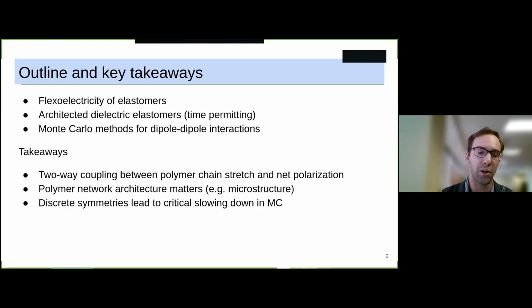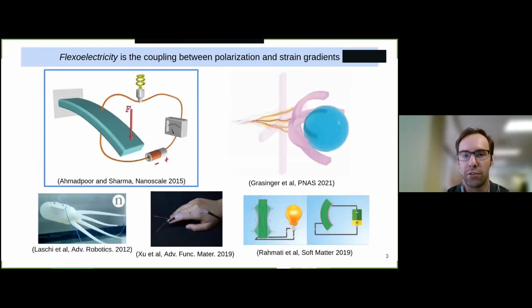I want to convey the fact that polymer network architecture matters. We typically think of elastomer networks as the chains being randomly distributed in every which direction, but I'll talk about ways in which you can design the microstructure to enhance the performance of the material. And then I'll talk about Monte Carlo methods, and as I said, some of the challenges. One of the principal challenges is that when you have discrete symmetries in your thermodynamic system, this can really lead to challenges in terms of the rate of convergence of Monte Carlo simulation. And I'll talk about how we've been addressing that.